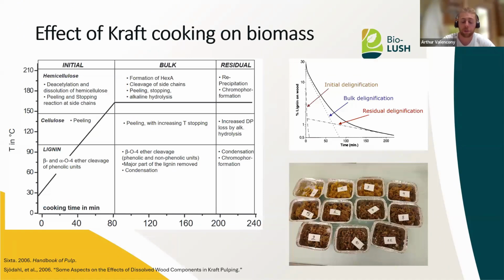So the kraft cooking can have different effects on the biomass. I will not explain all three stages of the kraft process, but we have three different delignification phases: the initial, the bulk, and the residual one. But the most interesting one is the bulk one, where we have the most lignin eliminated. And we can see in the bottom right images the different shape of the wood chips along the cooking, where we start from destructured wood chips to, at the end, pulp with individualized fibers.